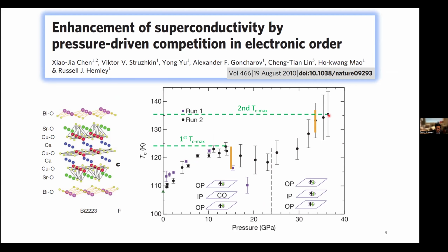It keeps going, then saturates at a pressure of around 36 GPa and hits another Tc max at around 136 Kelvin. The mechanism for the second resurgence of the Tc is that at lower pressure range, the inner layer of the copper oxygen plane is a competing order. When we go to higher pressure, it gets tuned into a superconducting order that favors the total superconductivity. So that's a very nice picture and also very beautiful results.